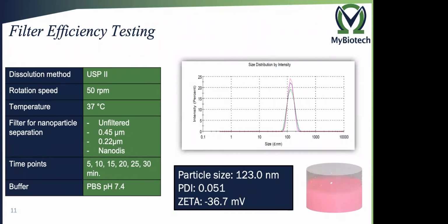Just a couple of pieces of information about the method we used and about the particles. On the left side, you see the method. We used the dissolution apparatus USP 2 with a rotation speed of 50 rpm at a temperature of 37 degrees. And we compared the unfiltered medium, 0.45 micrometer filtered medium, 0.22 micrometer filtered medium, and the NanoDisc. We took samples for 30 minutes every 5 minutes, and we used phosphate buffer at pH 7.4 as our dissolution medium. On the right side, you can see the particles.